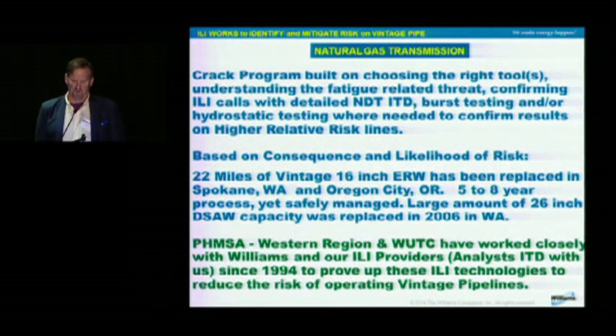So 22 miles of 16-inch ERW line were replaced in Spokane, WA and Oregon City, OR, but it was after a 5 to 8 year process, which included hydro testing, which included some significant burst testing, but we were able to safely manage that with ILI. A large amount of the 26-inch you may be aware of was DSAW. Capacity was replaced in 2006. A lot of that was pipe body cracking.